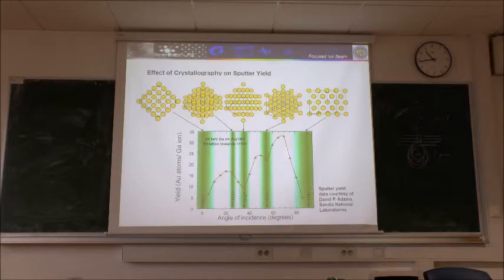Once more, this is a study of how this channeling influences the yield. In this case we have gold atoms and gallium ions. And these are the orientations of this gold. Gold is cubic. In one case, this is 001. This is that. We have relatively low yield, low signal. Why? Due to channeling. Because those gallium ions can penetrate inside and they do not produce secondary ions, secondary electrons, at the surface where we can measure.